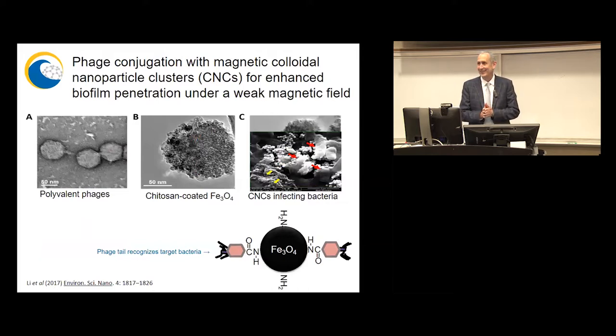So what we do is we conjugate these phages onto superparamagnetic nanoparticles that can be pushed in with a magnetic field, and you can control how far you push them in. Maybe you want them to go to the anaerobic part of the biofilm where that Clostridium difficile is residing, or maybe you want to turn right or left. And the point is that we're creating magnetic Trojan horses, okay? And there is one trick to this. The phages have to be pointing in the right direction. They have to be oriented so that the tail fibers are outward, because it is the tail fibers that recognize and infect bacteria.